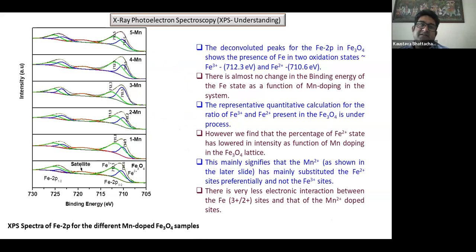Similarly, as I was telling you, if we take the individual peaks for the iron and deconvolute it, as we know, Fe3O4 has both iron +2 and iron +3, and being an inverse spinel structure, the iron +2 and iron +3 have their particular octahedral and tetrahedral positions. So the concentration of the Fe+2 and Fe+3 can be directly understood from the system, and we can see that as a function of Mn doping, the Fe+2 has a shift, whereas Fe+3 remains constant. So from this, definitely we can say that upon doping of Mn, the Fe+2 is being altered or changed. Both its intensity and its position get changed, whereas Fe+3 is not being touched by the Mn.